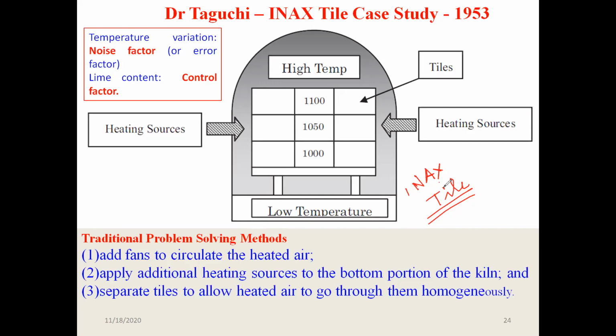They came to know that when the tiles are kept inside the furnace, the temperature of the furnace varies from 1000 to 1100. There is a variation of 100 degrees. So the variation of 100 degrees happens. The chemical reaction that happened within the ceramic was different, and there was a thickness variation.